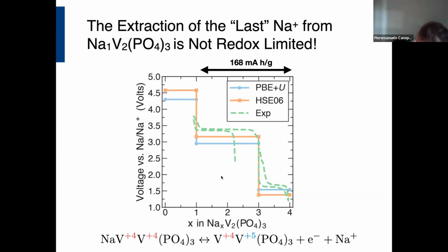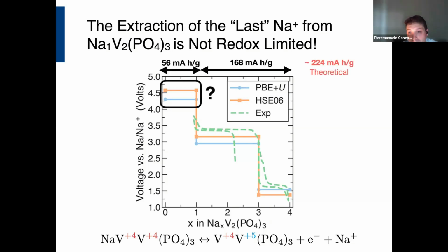This, of course, has been tested and experimented with for many, many years, but nobody has been able, at least with the traditional synthesis of sodium vanadium phosphate, to extract the last sodium. And this is important because when you go from sodium 4 to sodium 1, you can access a capacity, and here I'm using a bit of battery jargon, of 168 milliampere hour per gram. But if you were to access the last sodium, you could have another 56 milliampere hour per gram, and so reach a theoretical capacity of almost 224 milliampere hour per gram, which looks quite competitive, especially when you're operating at such a high voltage, at least, believe it or not, in the prediction, above 4 volts versus a sodium reference.